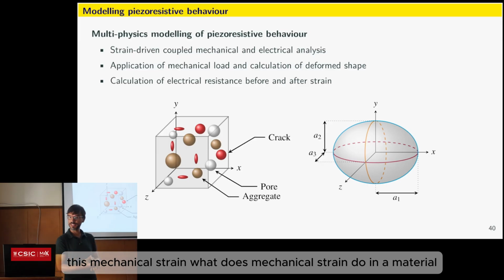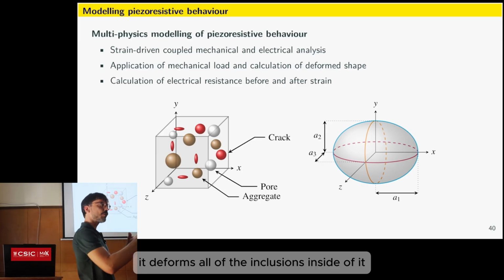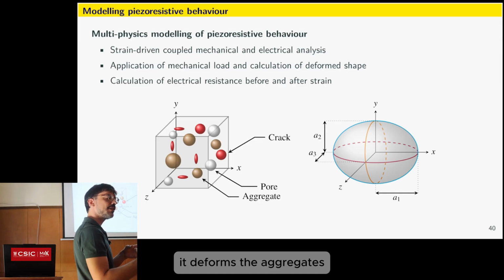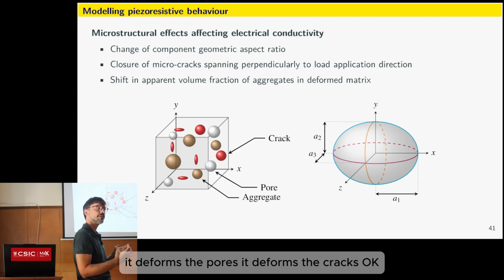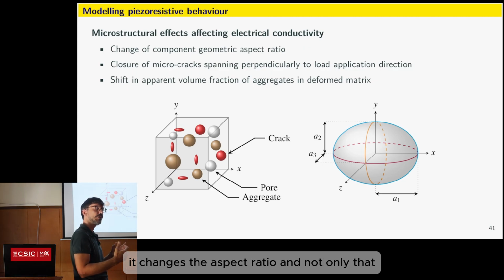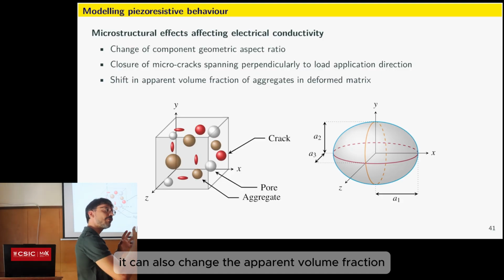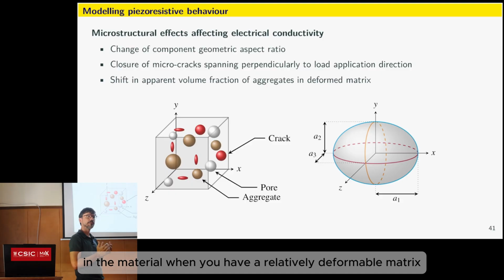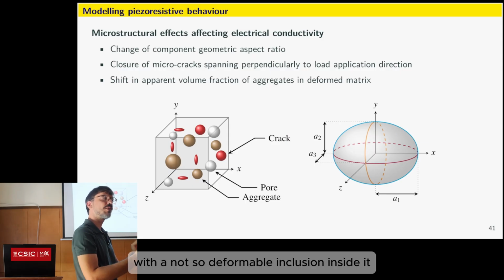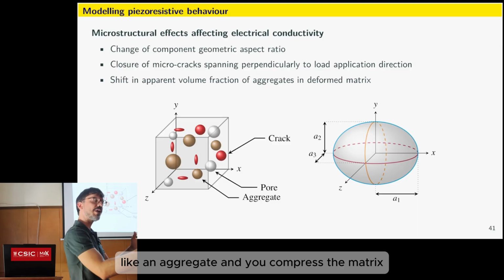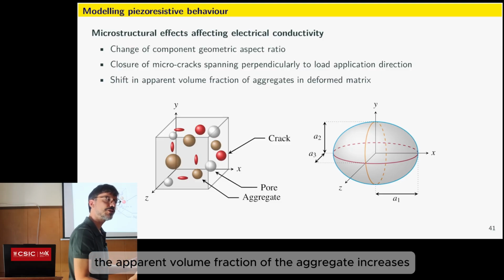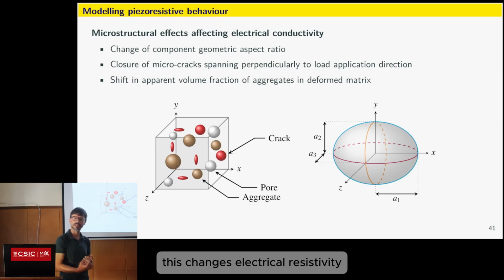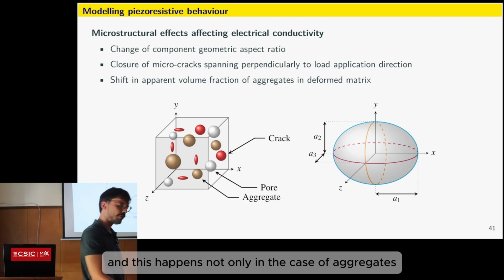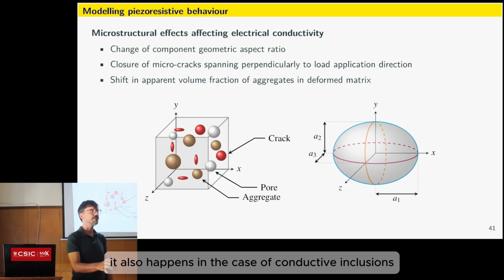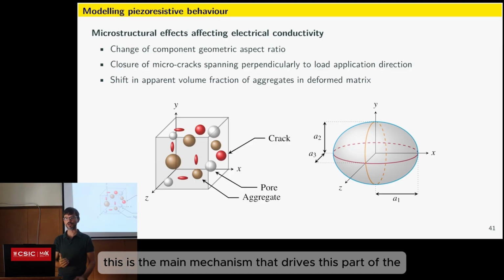What does mechanical strain do in a material? It deforms all of the inclusions inside of it. It deforms the aggregates, it deforms the pores, it deforms the cracks. Okay, it changes the aspect ratio. And not only that, it can also change the apparent volume fraction of each individual inclusion in the material. When you have a relatively deformable matrix with a not so deformable inclusion inside it, like an aggregate, and you compress the matrix, the apparent volume fraction of the aggregate increases. This changes electrical resistivity. And this happens not only in the case of aggregates, it also happens in the case of conductive inclusions. This is the main mechanism that drives this part of the response.